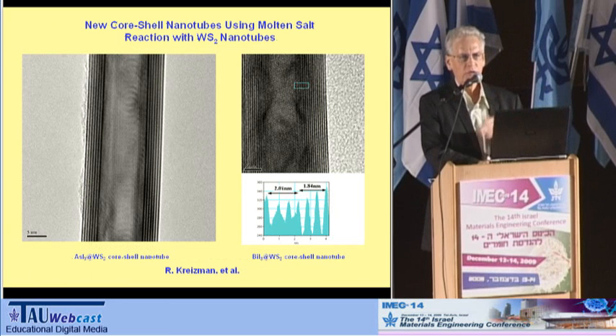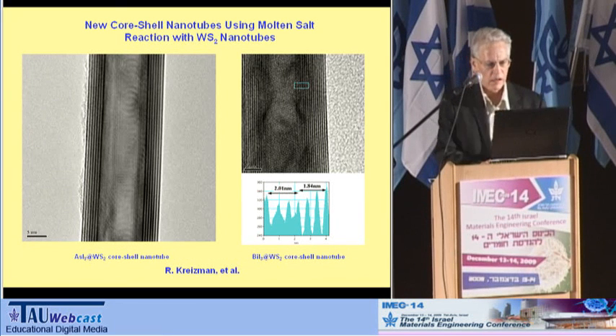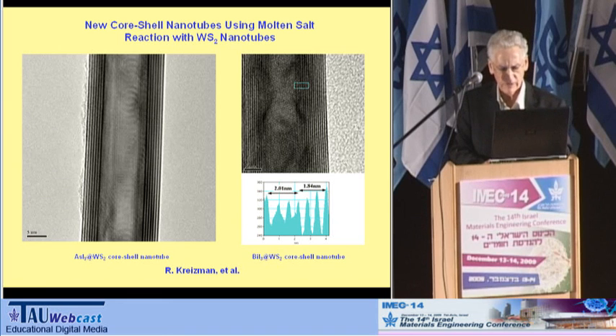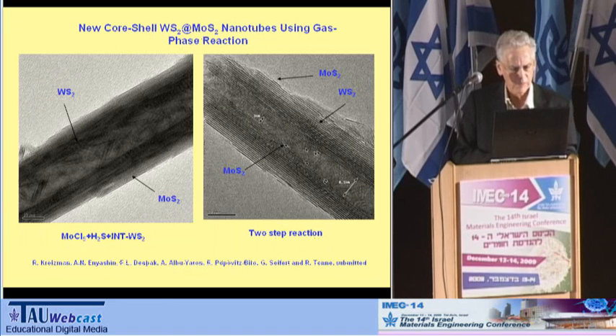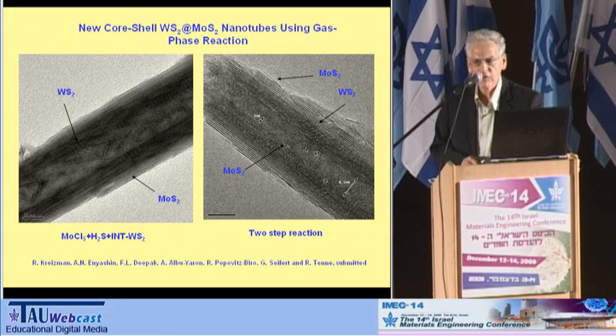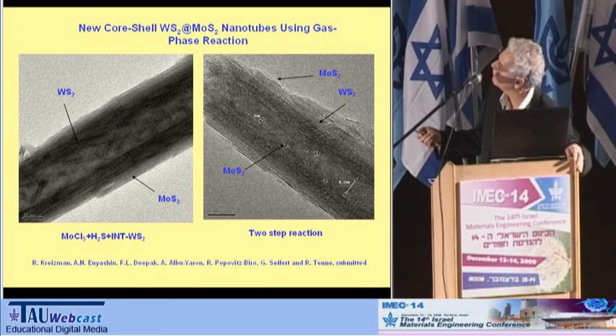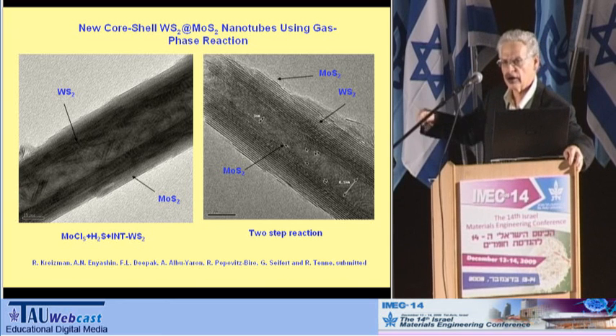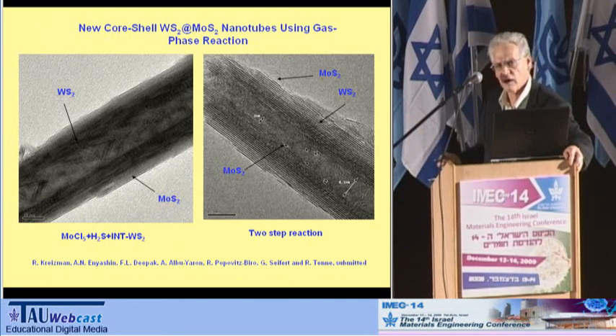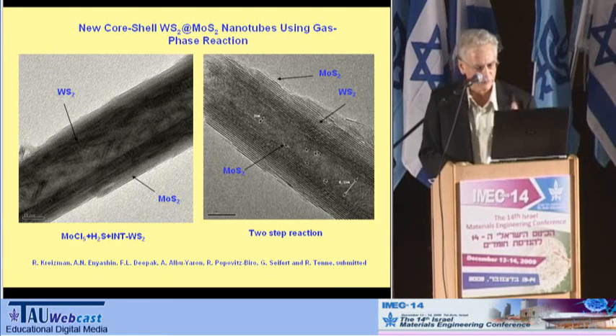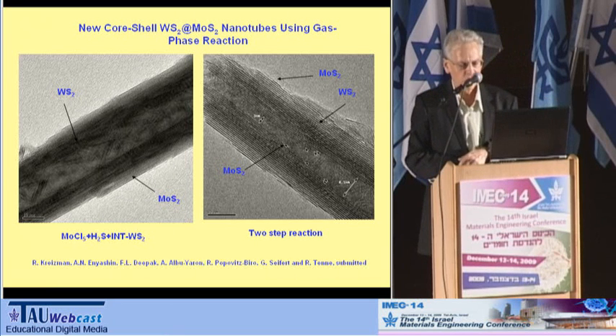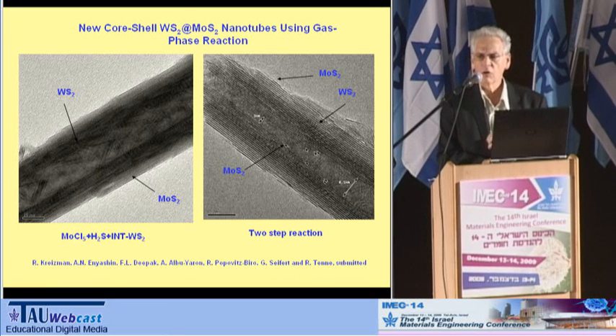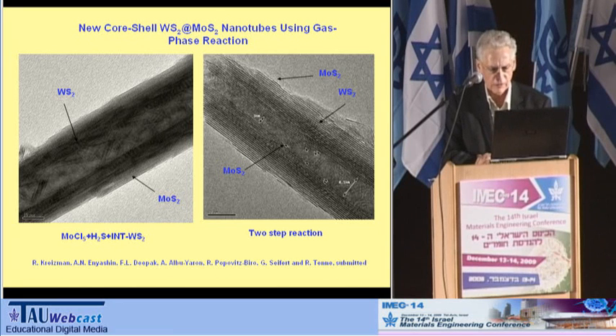And once you have this idea, you can try other nanotubes, and indeed we have observed different other iodide nanotubes which were templated into the tungsten disulfide nanotubes. We also did gas phase reaction, and we were able to grow molybdenum disulfide either inside or outside or on both sides of the tungsten disulfide. So we start to get superstructures, and that gives rise to a lot of interesting possibilities to do interesting physical measurements on confinement and on various other aspects which I will not elucidate at this time.